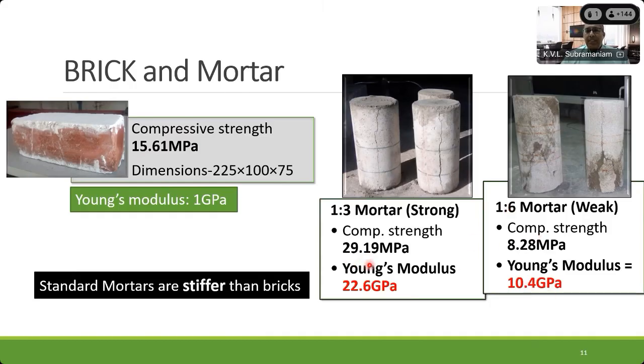And you can see the difference in the compressive strengths and the difference in the Young's modulus, which is the stiffness. Well, this is for the mortar. So you can see that when I made the mortar stronger, so when I went from the 1:6 mortar to the 1:3 mortar, it became stronger. Its compressive strength was much higher, but it also became stiffer. Again, this is expected from concrete-like materials.